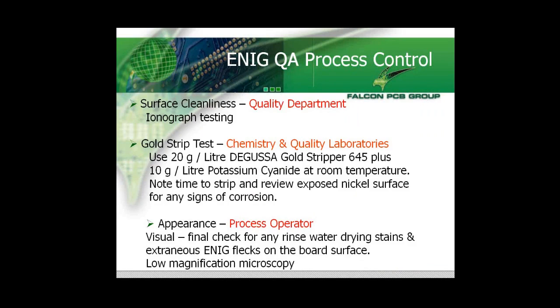Surface cleanliness is done by the quality department, and we do standard ionograph testing. The actual gold strip test, which was mentioned by Nigel, we tend to do this quite regularly. Again, we have a setup permanently in place, and we run it at 20 grams per litre. We use a Degussa Gold Stripper 645. We have done a lot of trials to check whether we are damaging the actual nickel surface underneath when we strip the gold, and so far we've found a process which we know actually works extremely well.